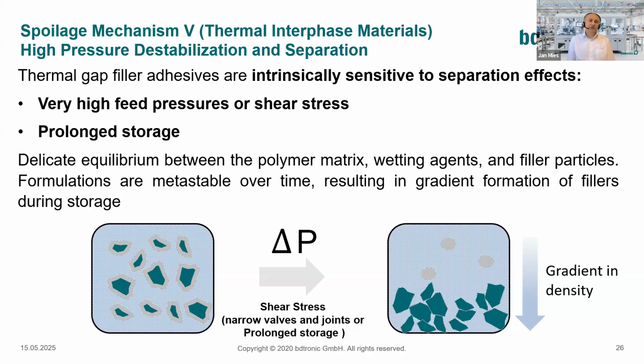I will highlight a little bit of what Till already mentioned, that those materials have a tendency of sedimentation, and they are intrinsically sensitive to separation effects. Why is that so? Remember, those materials have a very high filler level. And in order to get those materials stable, the formulation consists not only of the polymer matrix, but also certain additives, like wetting reagents. Those wetting reagents cover the surface of the filler particles so that they have a certain interconnection with the polymer matrix to get a stable formulation over time.